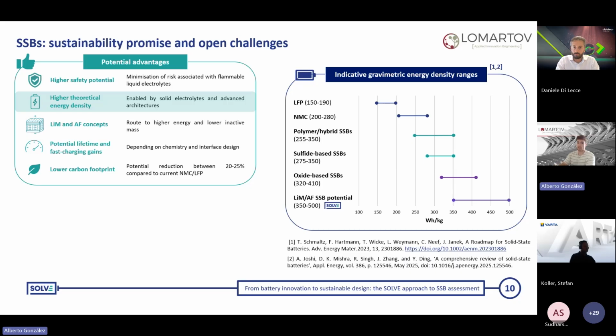This is shown in the graph on the right side. While current LFP and NMC lithium-ion batteries already provide good performance, we are approaching the theoretical limits, as mentioned before. And there are several SSB concepts, especially the ones with lithium metal and anode-free configurations, that theoretically can reach higher gravimetric energy densities. This is important for mobility because obviously higher values of watt-hour per kilogram can translate into either longer driving ranges or lower battery mass for the same energy capacity.